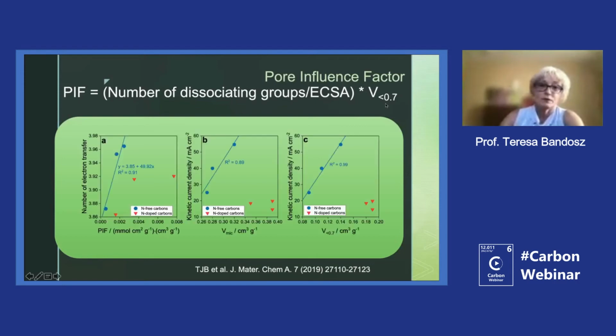And so we use this factor, which is important for the transport of the electrolyte, and also the volume of the pores smaller than 0.7 nanometers. And here is the dependence. So we look at the number of electron transfer, and we look at that PIF, and we found that for nitrogen-free carbons, we have a really good relationship.